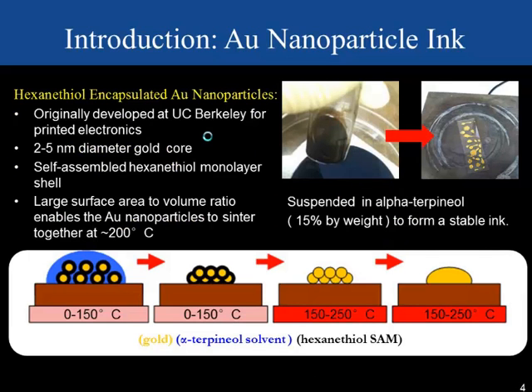Just to introduce our ink, we synthesized in-house a metal organic gold nanoparticle ink based on some work originally developed at UC Berkeley for printed electronics. It consists of a 2 to 5 nanometer gold core with a self-assembled hexanethiol shell. This monolayer is used to enable the nanoparticles to be suspended in solution to form a stable ink. An interesting property of these nanoparticles is that the small size and large surface area enable the nanoparticles to begin to sinter together well below the bulk melting point of gold. Understanding the thermal processing is then important for our steps.